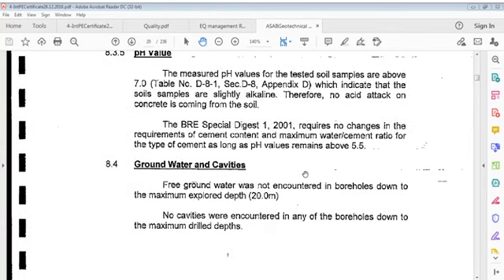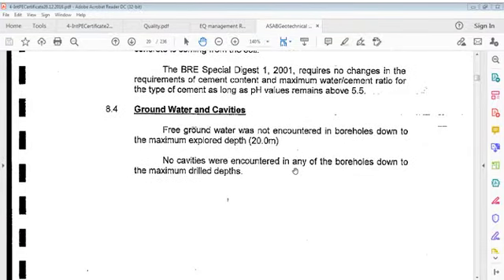pH value. Measured pH values for tested soil samples are above 7, which indicates that soil samples are slightly alkaline. Therefore, no acid attack on concrete coming from soil is possible. Concrete may be free from acid attacks. BRE Special Digest 1, 2001 requires no changes in requirements of cement content and maximum water cement ratio for type of cement as long as pH values remain above 5.5. So there is no problem in requirement of cement content and maximum water cement ratio for type of cement as long as pH value remains above 5.5.